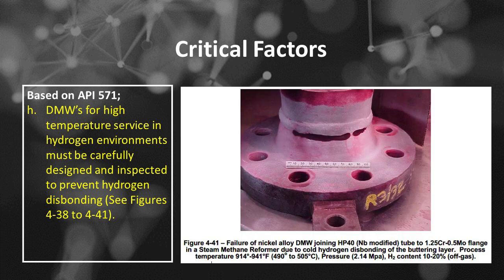See Figure 4.41, failure of nickel alloy DMW joining HP40, Nb modified, tube to 1.25 Cr 0.5 Mo flange in a steam methane reformer due to cold hydrogen disbonding of the buttering layer. Process temperature 914 to 941 degrees Fahrenheit, or 490 degrees Celsius to 505 degrees Celsius, pressure 2.14 MPa, H2 content 10 to 20%, off gas.